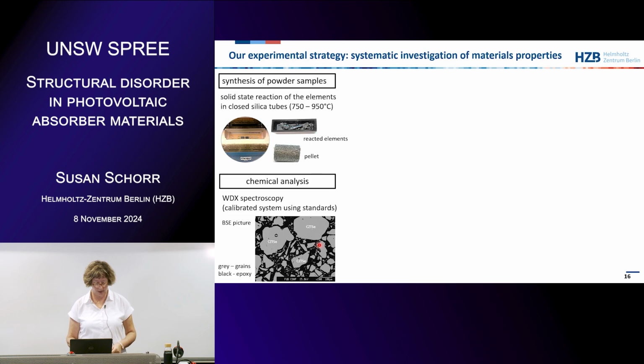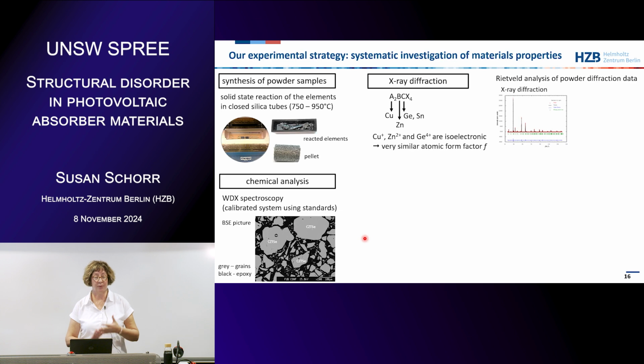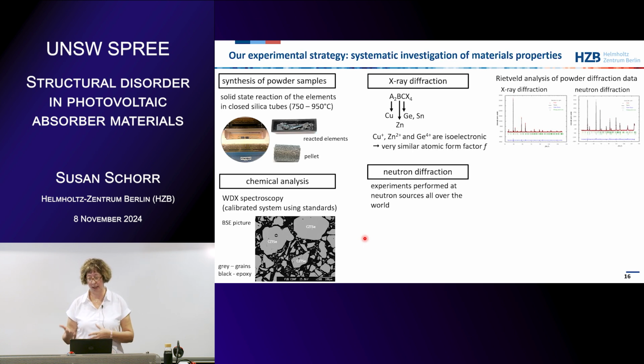The picture here is just an example: these gray parts are the grains of copper zinc tin selenide, and the black part is just the epoxy where the grains are embedded. Then we do X-ray diffraction on all samples, also to check the quality of the material. And because we have these isoelectronic cations, we then have to add neutron diffraction, if the sample has the quality of being homogeneous with respect to the quaternary phase.